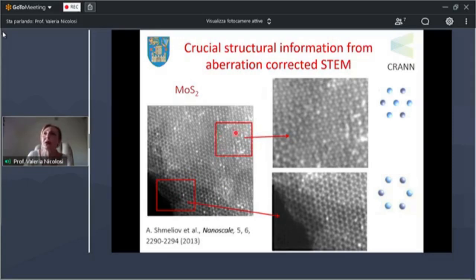So in this case, for example, if you zoom in, you see that the hexagons here are occupied. The central part of the hexagonal pattern is occupied by an atomic species, by sulfur atoms here. While in this case, you would have a perfect hexagonal type of structure. What we learned is that you have indeed stacking variations across the different areas of the flake. So again, we learned that we could use this type of exfoliation methodology to make plenty of materials that we could make into composites or other types of applications, but not in microchips, not in electronics that was seeking high mobility, for example.